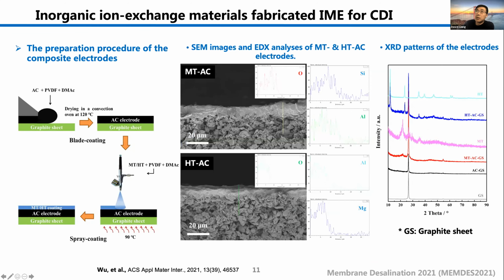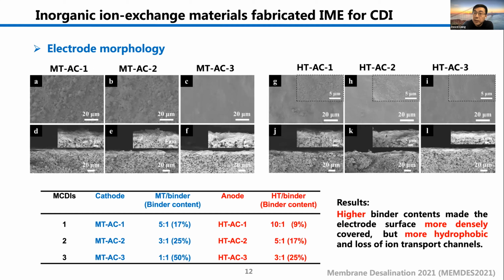Okay, let's come to the result part. Both the SEM image and the EDX analysis successfully showed the coating of the MT and HT on the AC electrode. And XRD patterns also prove the successful coating. We also investigated the binder content effect because it needs the binder to make the thin layer. We tried using different ratios of the ion exchange materials with the PVDF as the binding solution.